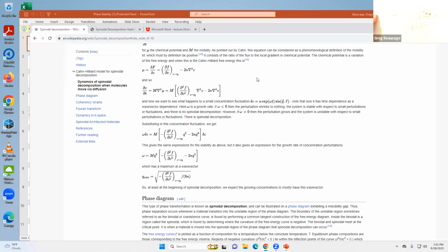Q max for this growth. And then you can plot the intensity at Q equals Q max versus time. That's going to give you the growth rate, because the growth rate equation is exponential, e to the RT, so if you take the log of the intensity, it would be a straight line. You can get the slope of that to get the growth rate, which will be the argument of that exponential.